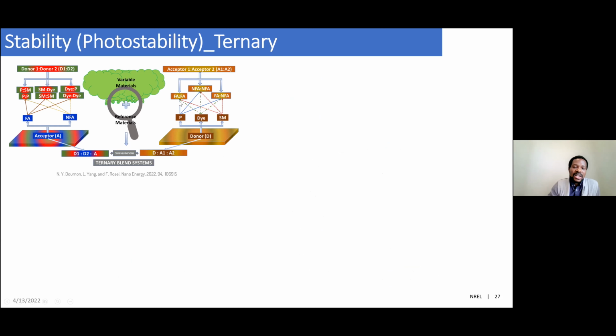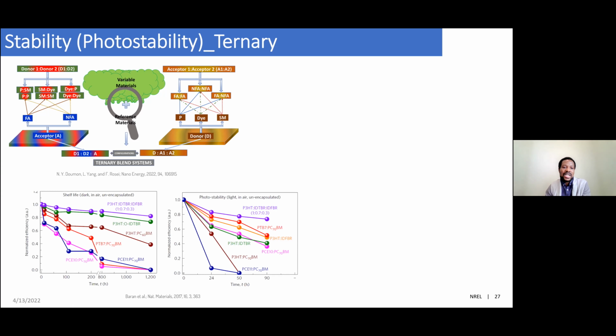But these challenges have been discussed in this review, where a lot of the work that has been done has been captured. But to only show you a few, you can see that Baran et al. also show that in air and unencapsulated devices with different composition using P3HT and two other non-fullerene acceptors or molecule, you could have a good shelf lifetime in air compared to other binary systems. So it shows that ternary system could be a way to go. And then also under sunlight, in air, they have also showed that ternary blend outperform the rest.